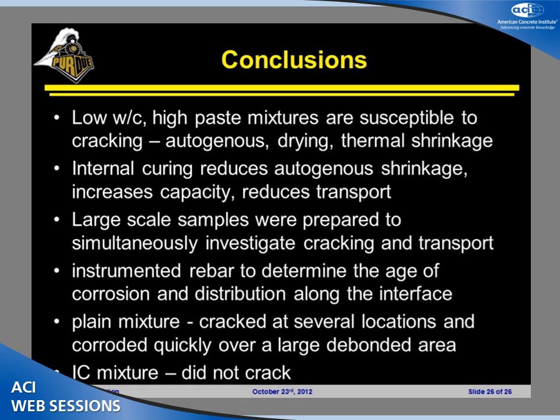Could you reduce the thickness? I think it would be possible to start reducing thickness, but it depends on what your limitations are. If your thickness limitation is really driven by cover depth, then you've got to do your calculations to figure out, if I've got a concrete that's more dense, how does that relate to a 0.45 water to cement ratio? There's something you can gain there, but that's not the direction that we've really looked at. We've been really saying, can I take a bridge deck that's being replaced or being resurfaced at 25 years and make a 60-year solution? That's really what we've been looking at.